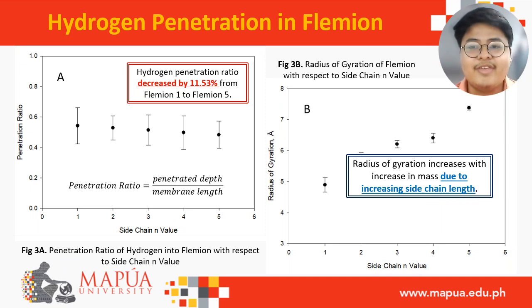With the validated structures, we determine the hydrogen penetration. Here in figure 3a, we can see that hydrogen penetration ratio decreased by 11.53% from Flemion 1 to 5, where the penetration ratio is defined as the penetration depth over the membrane length. This suggests that longer side chain lengths decrease the penetration, meaning that hydrogen is not able to penetrate as deep with longer side chains as they act as an obstruction.